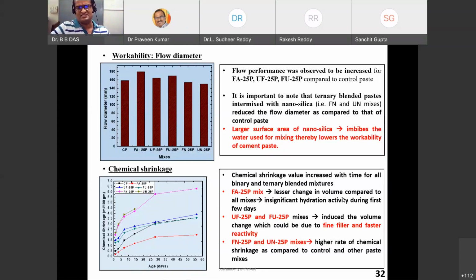Fly ash 25 shows lesser change in volume compared to all mixes, with insignificant hydration activity during the first few days. For fly ash mixes, the volume stability is much better. Lesser change in volume means shrinkage is going to be minimized, so there may not be any problem with shrinkage. That is understood. Now, when you go with ultrafine fly ash, there is induced volume change, which could be due to its finer size and faster reactivity. Again, the moment I introduce nanoparticles or nano-SiO2, there is a higher rate of chemical shrinkage as compared to control and the others.